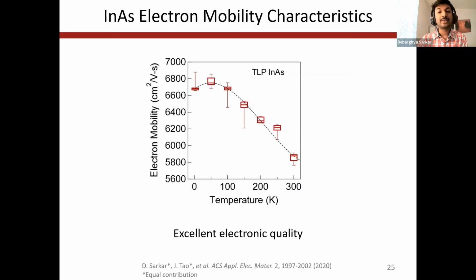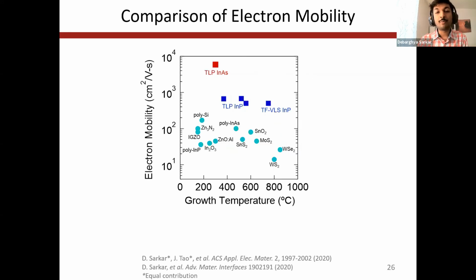Indium arsenide grown by this method has electron mobility of about 6,000 centimeters squared per volt second, measured at room temperature. To put it into perspective, this is a compilation of the highest electron mobilities measured from different material families directly grown on an amorphous substrate. As can be seen, the TLP grown materials have higher electron mobilities than all of them. In fact, the TLP grown indium arsenide has the highest electron mobility, being about 2 orders of magnitude higher than the majority.